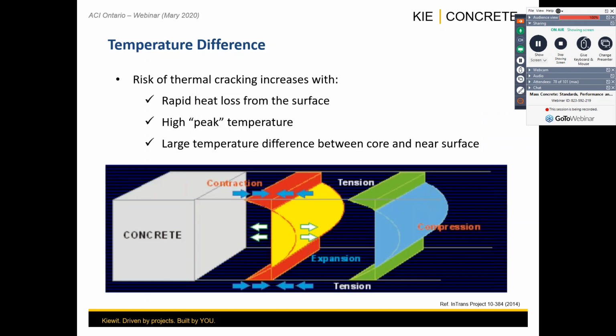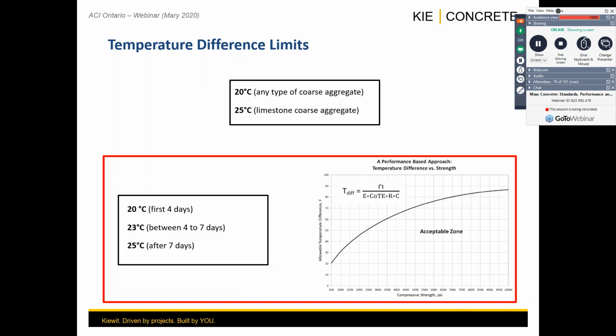Now then, if we create a large temperature difference at the surface, the tension on the surface is going to lead to cracking. So in simple terms, what are we saying with the temperature differentials of the CSA standard? Celsius, coarse aggregate, any type of concrete, coarse aggregate, because typically when you start seeing the coefficient of thermal expansion, when you get into limestone coarse aggregate, you're going to do testing and you're going to find likely that you're below the 10 millionths per degree Celsius for the coefficient of thermal expansion.